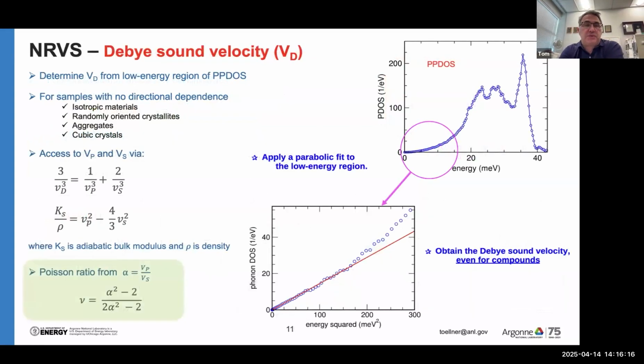One of the quantities of interest for some geoscientists is the Debye sound velocity. This is determined from the low energy region by looking at the curvature of that Debye spectrum, of the density of states in that region. Once you have the Debye sound velocity, you can get the compression and shear velocities from the equations on the left. You have two equations and two unknowns, and you need to provide the adiabatic bulk modulus and the density. Density is typically gotten from diffraction data, which can be taken at the beamline, and so then one can get both shear and compression velocities, and then you get the Poisson ratio as a benefit as well.